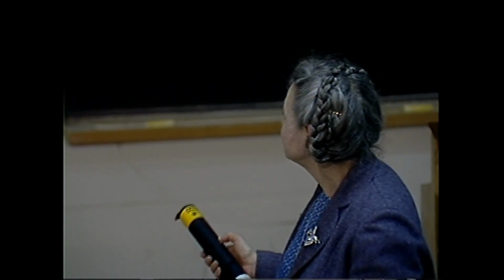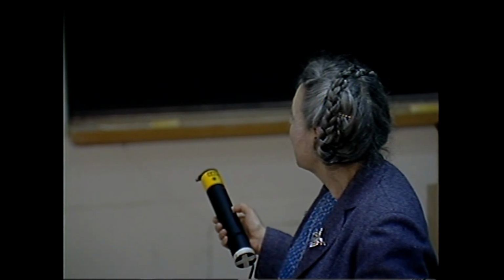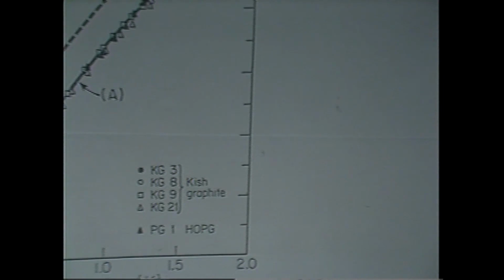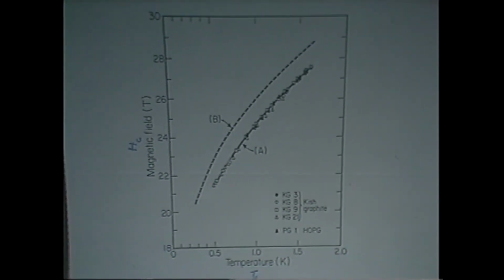And here's the anomaly, you see. It happens at high fields, close to 25 Tesla. And it is not a one-electron phenomenon. Why isn't it a one-electron phenomenon? Because one-electron phenomena don't have much of a temperature dependence, but this thing has a big temperature dependence. And here's the dependence of that anomaly. Well, here's the magnetic field where the anomaly occurs as a function of temperature, and it has quite a wide range of field dependence. And in fact, the functional form is a BCS-type form.